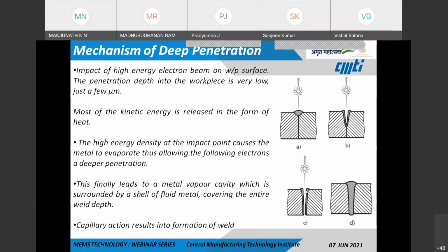So here we can see that this entire hole is covered by a sheet of molten metal. With the action of capillarity, this molten pool again rises up to form a weld, and you can see the bead formation. That is because of the capillarity action of this weld.